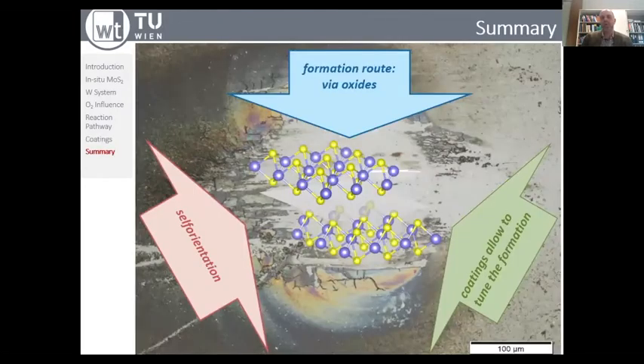And to make a kind of a summary now. When you are looking at the in situ formation of tribofilms in these two systems, it highly depends on, as I said, first, you need to have a formation route via oxides, especially for the tungsten. This is decisive. As I could show you, if you don't have a pre-oxidized surface or something that has a high surface oxidation rate, you will not be able to form in situ the tungsten disulfide. You also need, of course, a respective additive source that provides you with the sulfur. You also have to provide, of course, the tungsten or molybdenum by itself.